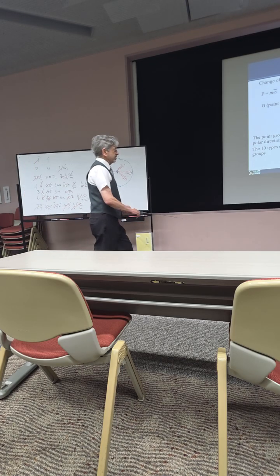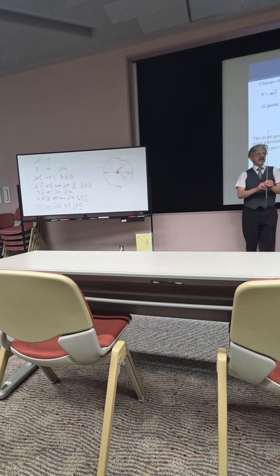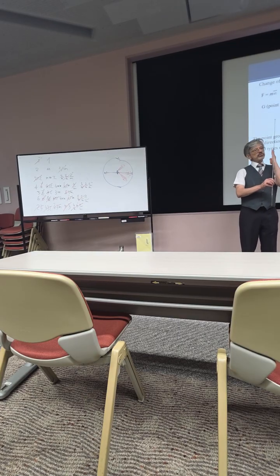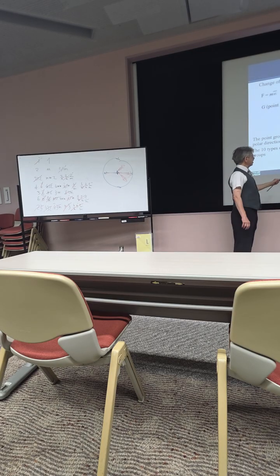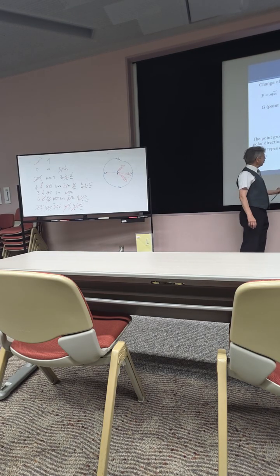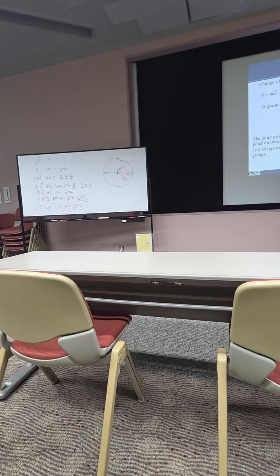And if you look at the list here, you simply see that there is one axis alone, or one axis with a mirror that contains this axis, but nothing perpendicular. So you have identity, axis of order 1, or one mirror. 2-fold rotation axis, or 2-fold rotation axis with 2 mirrors. 3-fold, or 3-fold with 3 mirrors. 4-fold, or 4-fold with 4 mirrors. 4mm, sorry, there is an mm missing here. 6 or 6mm. These are the 10 pyroelectric groups.